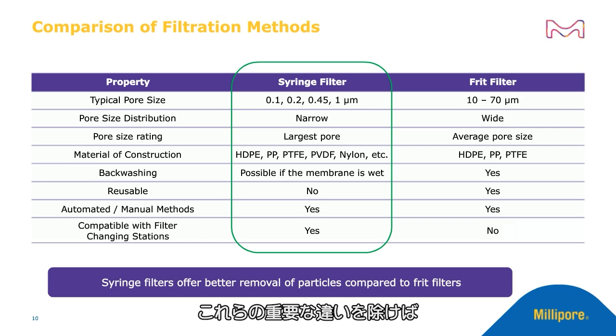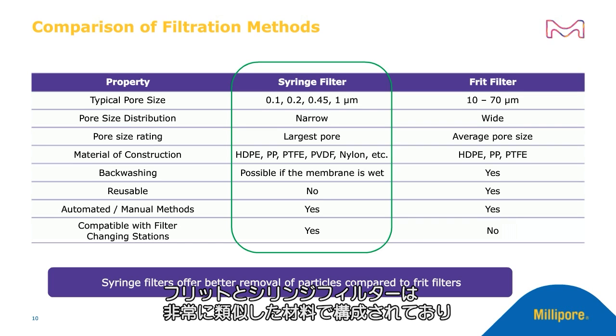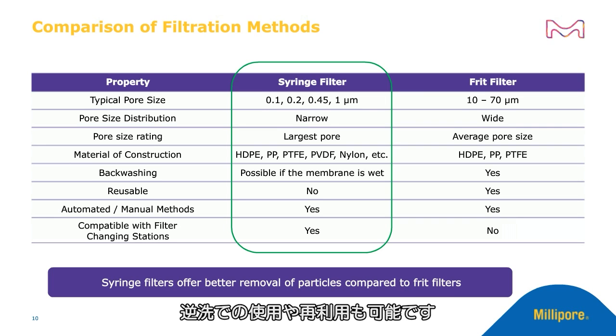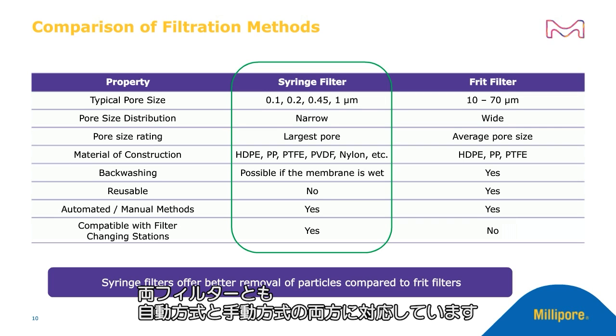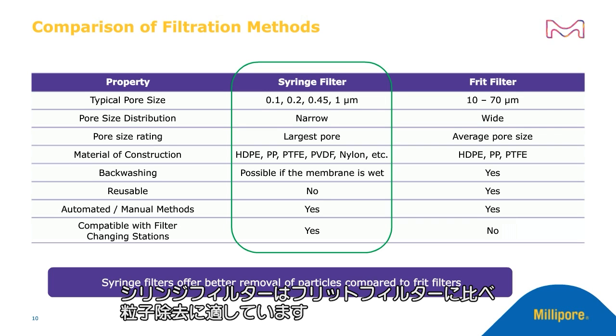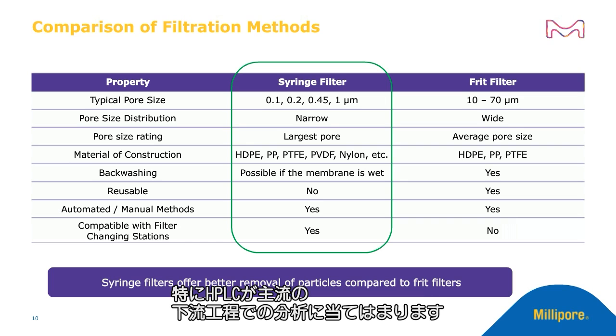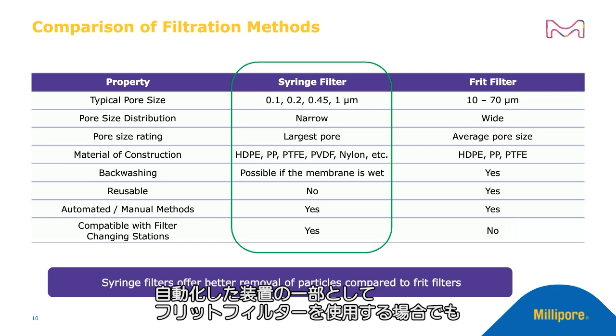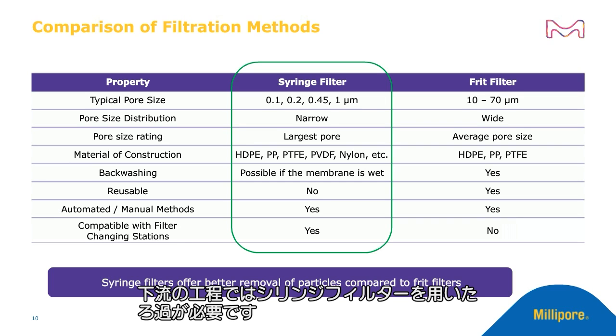Other than these two key differences between the frit and syringe filter, they have very similar materials of construction. They can be used in backwashing. Sometimes they can also be reused. And both frit and syringe filters are compatible with automated and manual methods. Overall, what we have observed is that syringe filters are better suited for particle removal compared to frit filters. And especially with HPLC becoming the dominant downstream analytical technique, even if frit filters were used as part of an automated solution, further downstream filtration using syringe filters is still required.